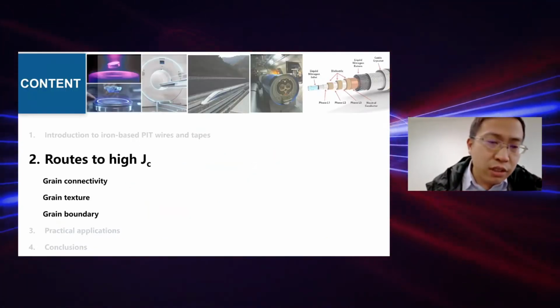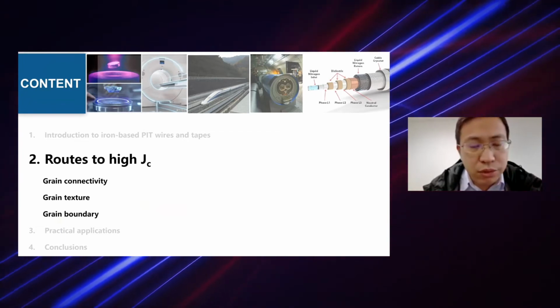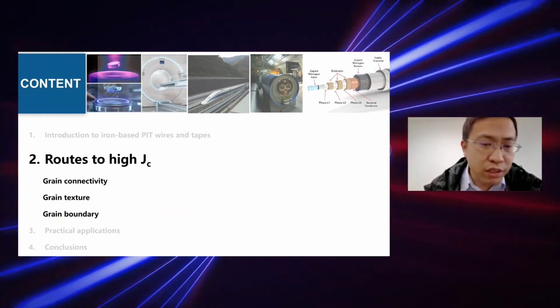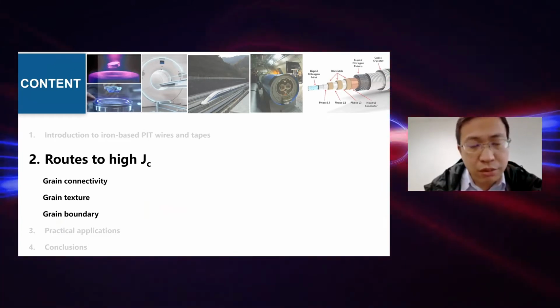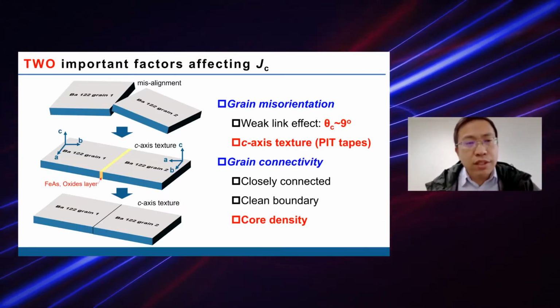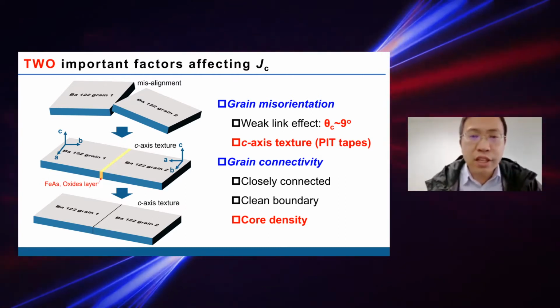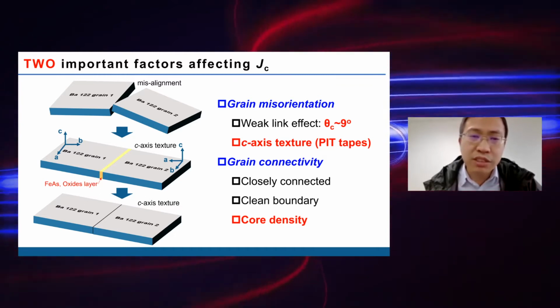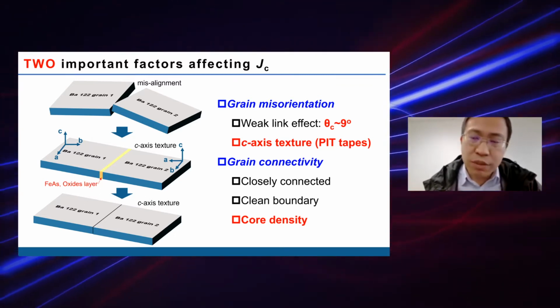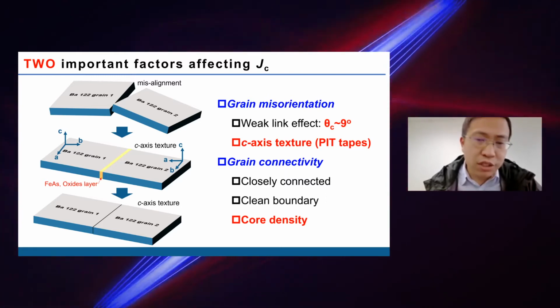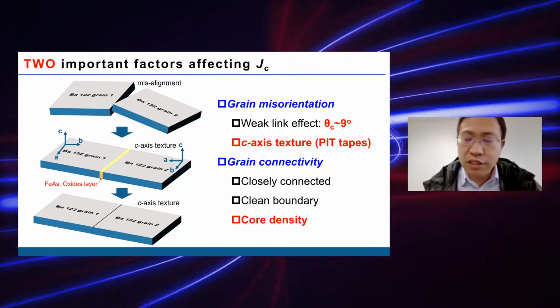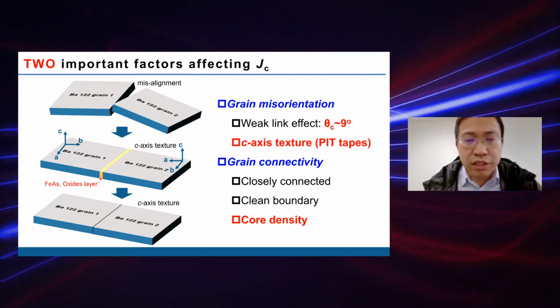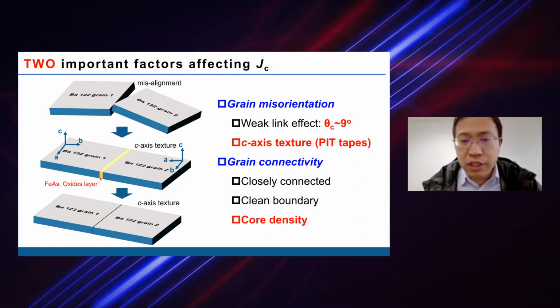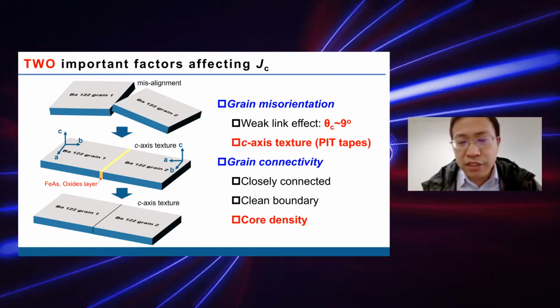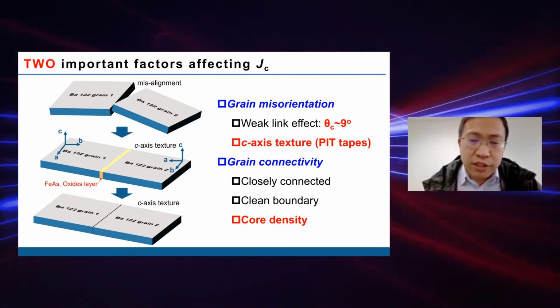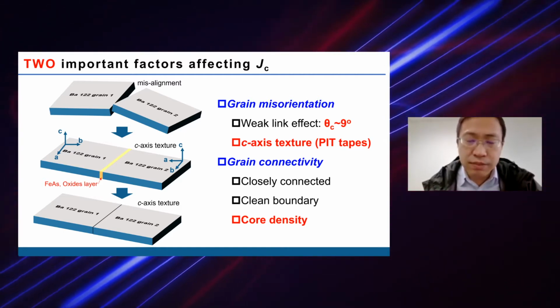Then I will talk about the 3 routes to achieve a high Jc, including grain connectivity, grain texture, and grain boundaries. As we know, there are 2 important factors affecting the Jc of iron-based superconducting wires and tapes. The first one is the grain misorientation. When the misorientation angle between adjacent grains is larger than 9 degrees, the intergrain current will be largely decreased. So for now, we can achieve a partial c-axis texture in the PIT tapes.